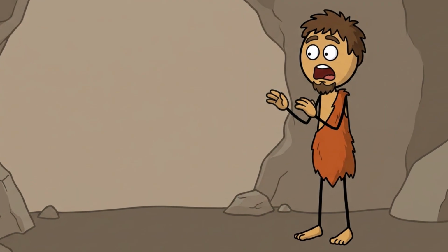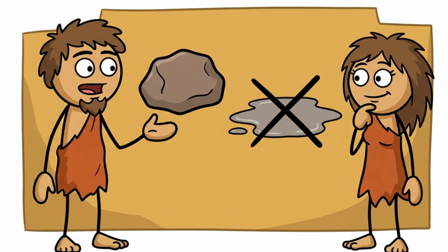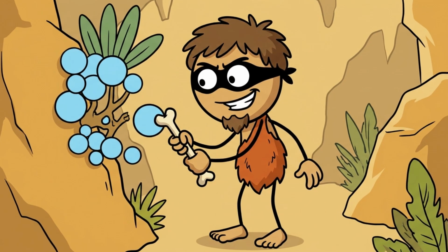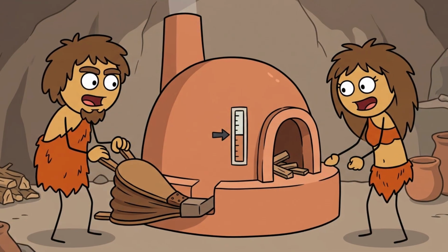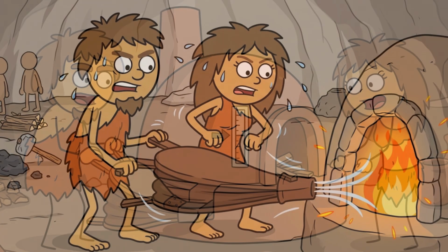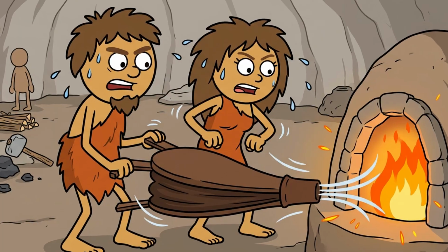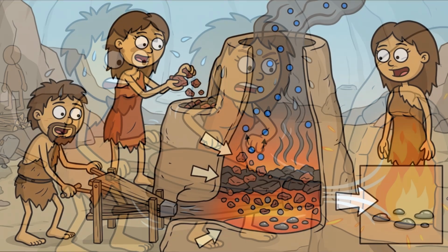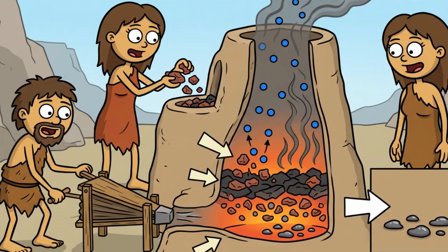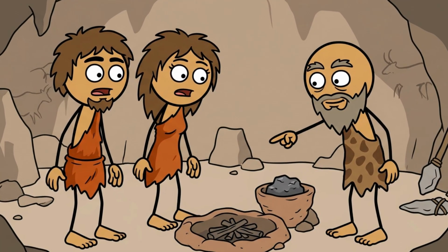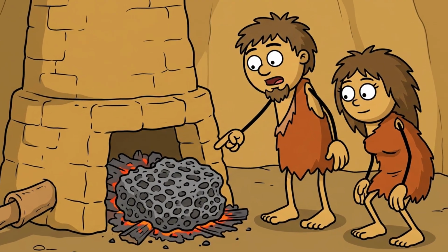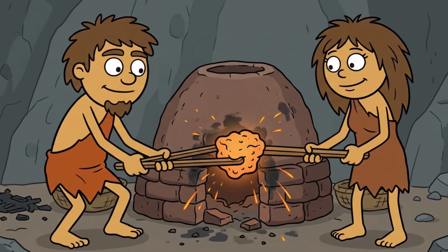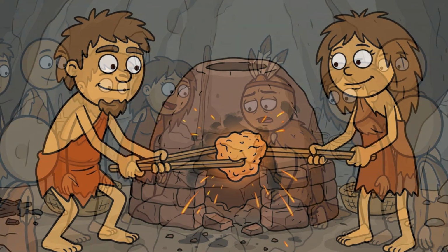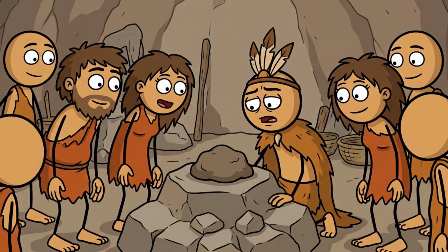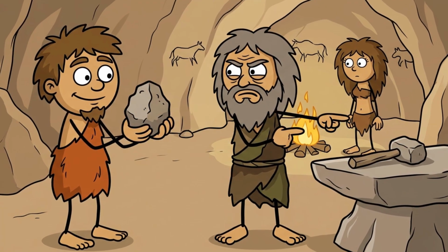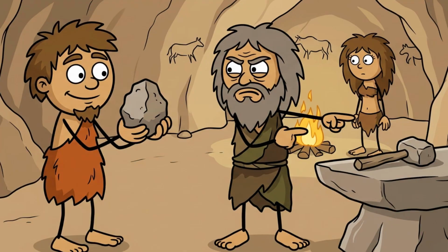You never actually had to melt iron. You only had to convince it to let go of its oxygen. At around 1100 to 1200 degrees, well inside the range of a charcoal furnace with bellows, the carbon monoxide gets to work. The iron oxide gives up its oxygen. But because you are hundreds of degrees below melting point, the iron that appears does not run out as a liquid. It arrives as a spongy, glowing, porous mass, riddled with holes and mixed through with waste, sitting in the bottom of the furnace. That mass has a name, a bloom, and a furnace built to make one is a bloomery. What comes out is not a usable object.